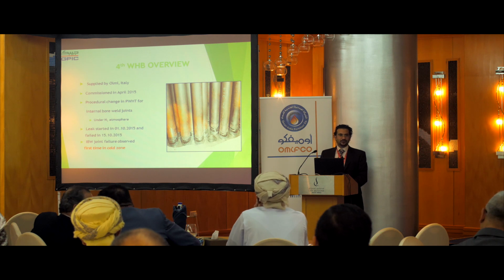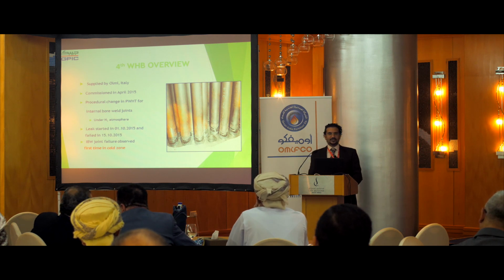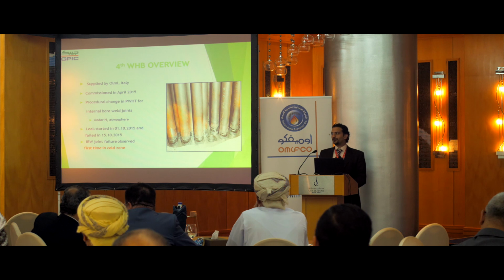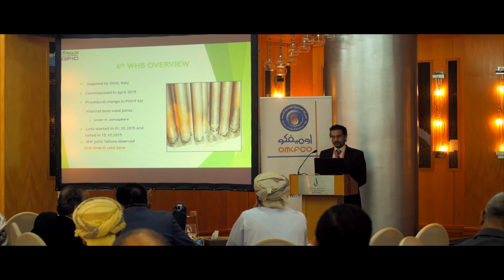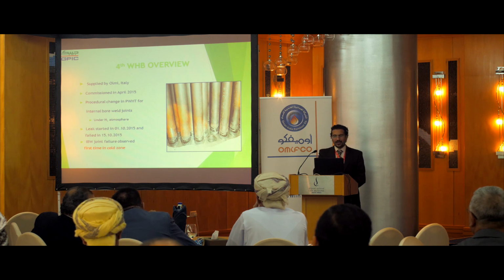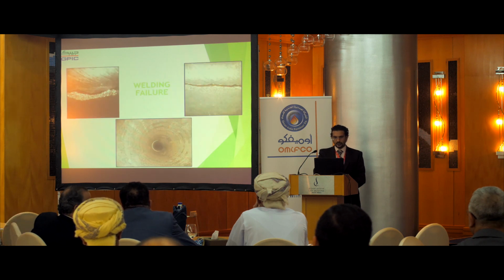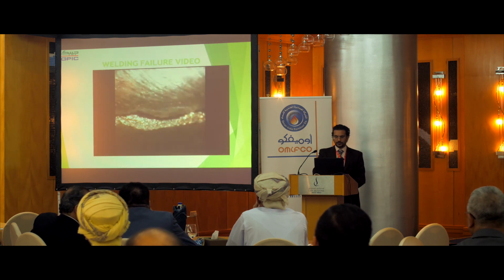However, six months after startup, a leak started. We found it from the conductivity that was increasing. And two weeks later, the tube failed. And this is the first time we got a leak in the cold zone. So this is the welding failure we found after looking through the tubes, with boroscopy.